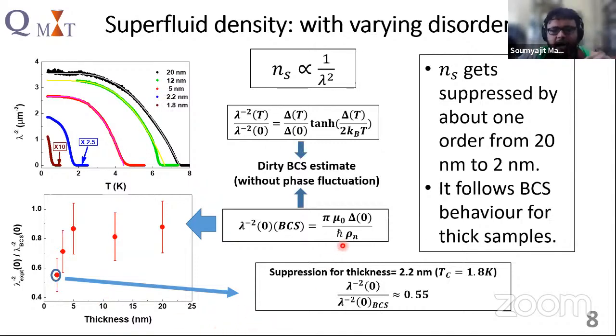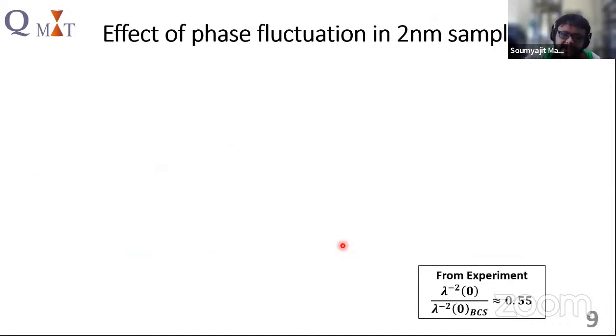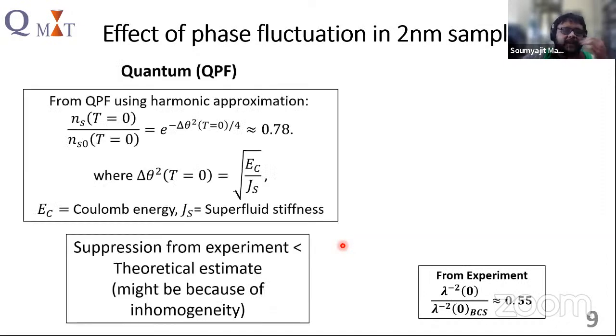Okay, yeah. So then the suppression is like 50%. The suppression for the 2 nanometer sample is like around 50%. So we have estimated the suppression from the experiment by the quantum fluctuation approximation. The calculation, it is coming like 0.78.